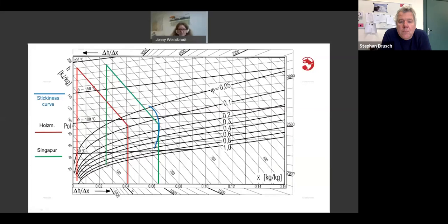We do the same in Singapore. In Singapore, we had 30 degrees C and a high relative humidity of 90%. So this is our starting point here. We heat up the air in the same way to 190 degrees C. You see, we have now moved just by heating up the air. In this case, we are just very much more on the right-hand side of the diagram, which means our whole system is more moist, right from the beginning.